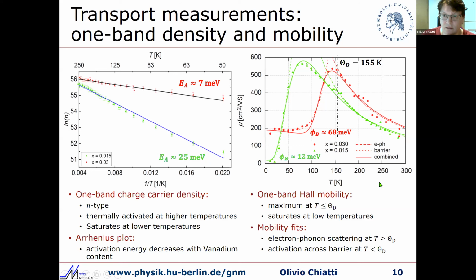In the mobility, the picture is a bit more complicated, and it's a hint that maybe a one-band analysis is not entirely suitable for this system. We see at high temperature that the temperature dependence fits very nicely the electron-phonon scattering in semiconductors. At lower temperatures, it's more complicated. It looks like we have a temperature dependence consistent with an activation across a barrier, in addition to a constant offset. This could make sense if you assume that the surface states are shunting the bulk conduction, and the bulk conduction has a barrier-like activation.